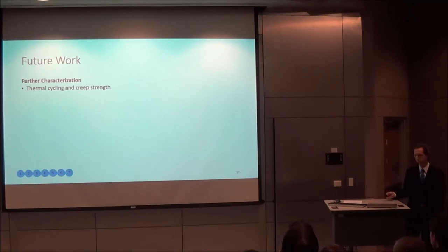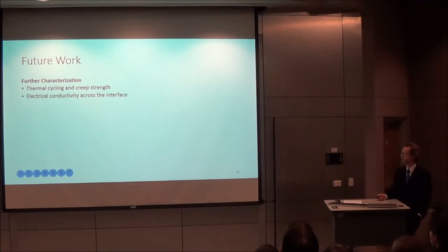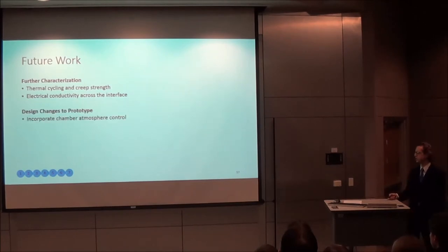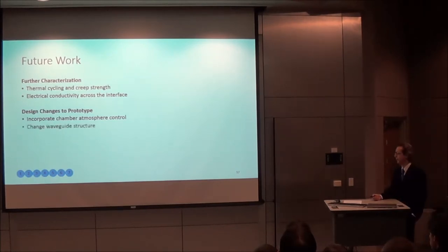Thermal cycling is important for such a joint in electronics applications, and determining its creep strength would be important, as well as evaluating the electrical conductivity across the interface. Some design changes to the prototype that could be made: the incorporation of atmosphere, removing oxygen or removing the atmosphere completely or raising the pressure, can decrease oxidation of metal particles and reduce the melting point of the interlayer, as well as suppress arcing more effectively.